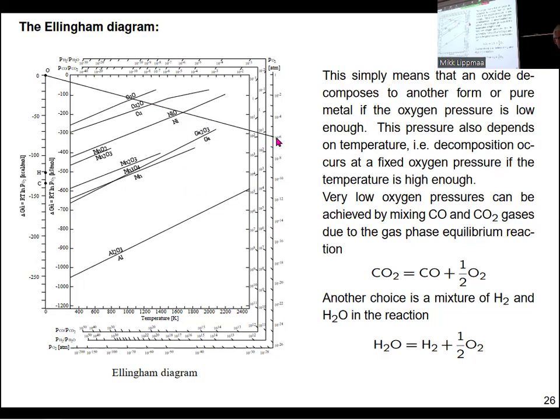In other words, if we are at 10 to minus 6 atmospheres, if we heat the system above 1600 Kelvin, so about 1,300 degrees C, then nickel oxide would reduce back to a metal. And if we are below 1,300 degrees C, then we would oxidize to nickel oxide. The lines end here because of melting. So the material melts, then the line ends.